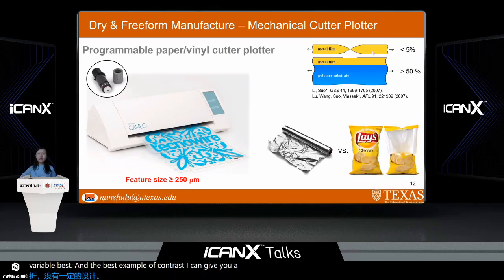However, if you support the metal thin film by a strong and well-adhered polymer substrate, you are able to achieve more than 50% stretchability without any fracture, without serpentine design. So it's intrinsically very robust. And the best example of contrast I can give you is aluminum foil, freestanding metal, versus this kind of potato chip bag, which is polymer-laminated aluminum. You can have a very intuitive sense which one is more stretchable.